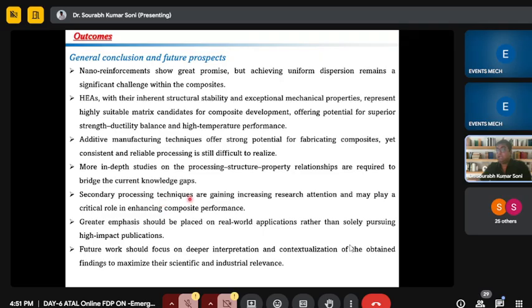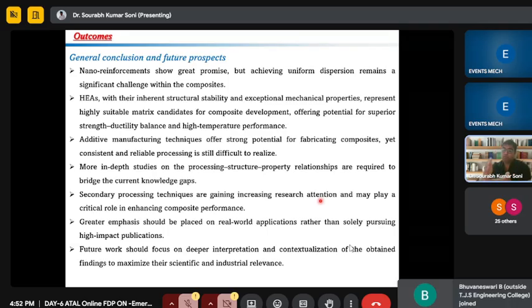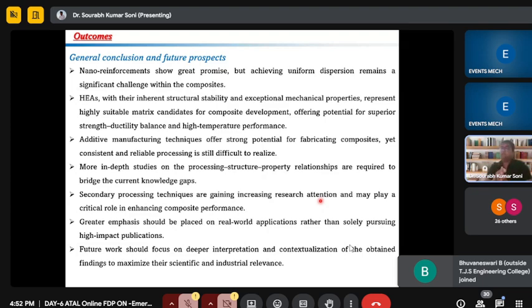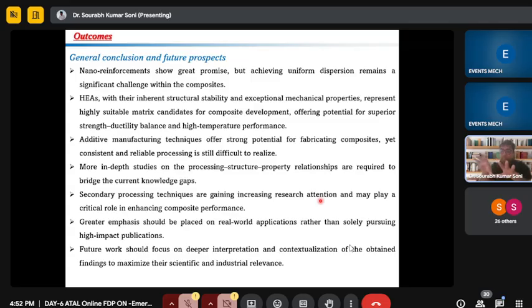Then secondary processing techniques are gaining increasing research attention. Yes, of course, because if we mix reinforcement into the matrix material, UTS increases but ductility decreases. But recently I observed that they achieved 1 GPa in a titanium matrix material with the help of secondary processing, meaning heat treatment. With cryogenic processing, heat treatment, hot rolling, and cold rolling, we can improve the properties of the resulting specimen or composite. So we must focus on secondary processing. It is costly, but we need to spend some time on that also.